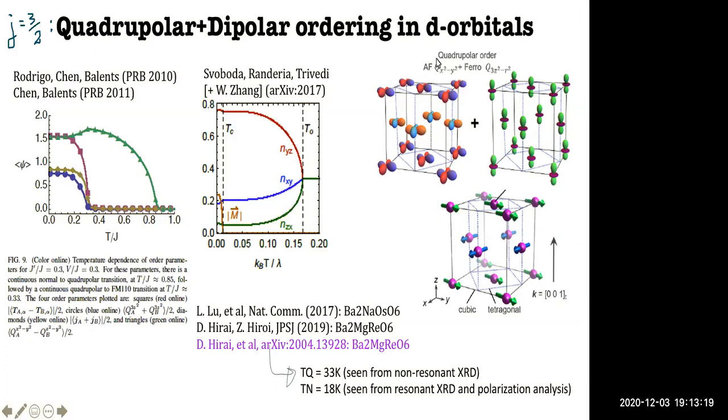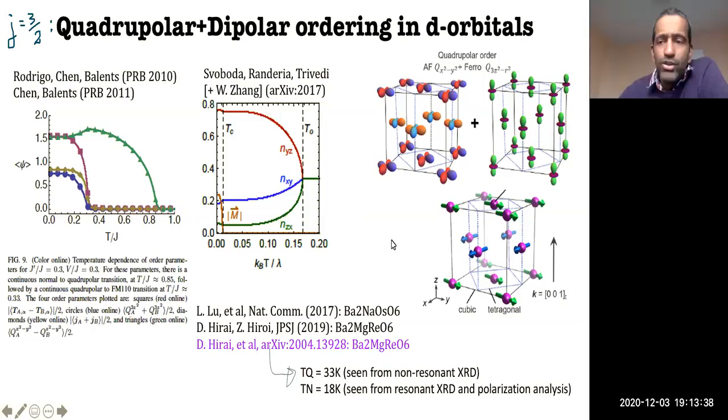So the idea is that this quadrupolar order sets in and affects the exchange coupling of the spin-spin interactions, and finally whatever the exchange coupling does, it dictates the nature of the lower temperature spin order. Is that right? Yeah, it should be, because the orbital order happens at a fairly high temperature compared to the spin order. So the exchange interactions are probably going to be quite different in the symmetric phase versus the quadrupolar ordered state.